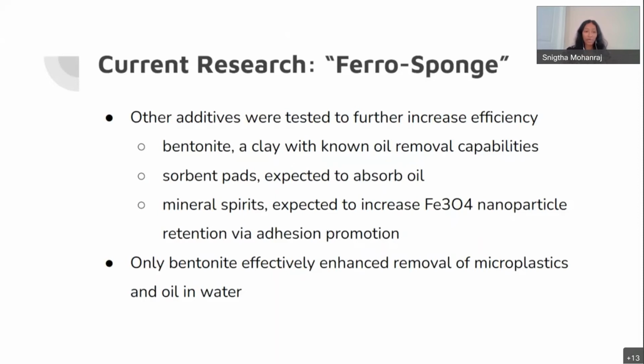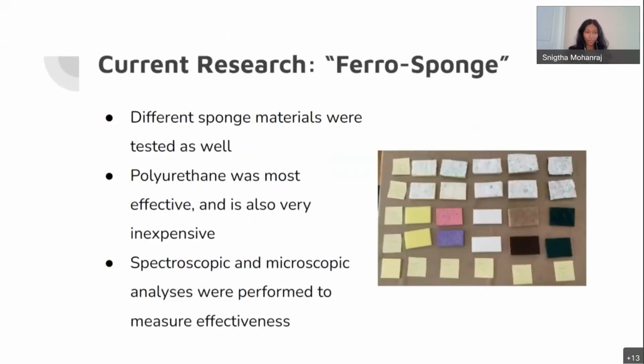The second one that I wanted to test was sorbent pads, which were expected to absorb oil. And the third was mineral spirits, which were expected to increase iron oxide nanoparticle retention, so it's an adhesion promoter. However, even though it was expected that all three of these additives would increase the efficiency of the ferrosponge the most, only bentonite was able to successfully enhance the removal of microplastics in oil and water.